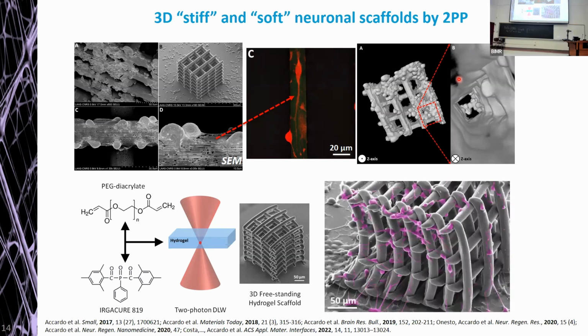In this way, it was possible to obtain much more well-ramified neuronal networks with the presence of multiple neuritic extensions per single cell, which I could not observe in the presence of the IP-Dip material. So that is an example of how the softness of the material plays a direct role on the evolution of the neuronal network.